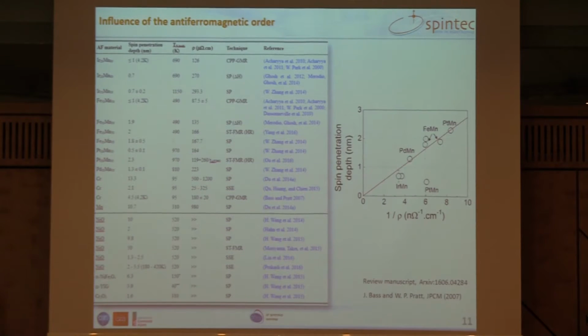So back to our spin penetration lengths. I'm not sure it's very easy to read this table, but these are spin penetration depths which were measured for different kinds of antiferromagnetic materials by different kinds of techniques. So in this graph, I plotted the spin penetration depths as a function of 1 over the resistivity for the manganese-based alloys that were measured by the spin pumping method. Okay? So same metallic family and same measurement method. And well, apart from platinum manganese, which remains a mystery to me, these data points fall on a straight line.